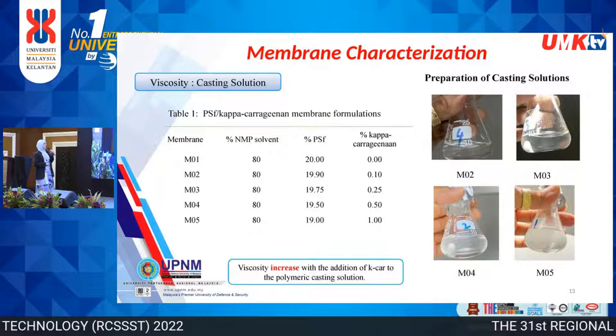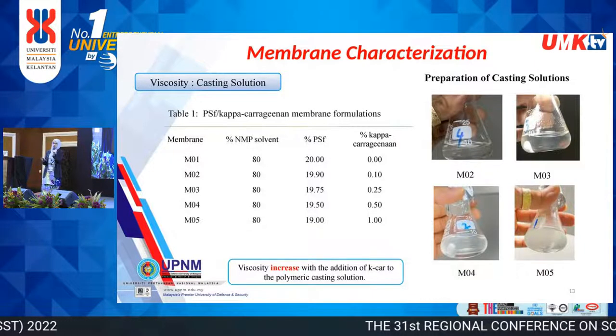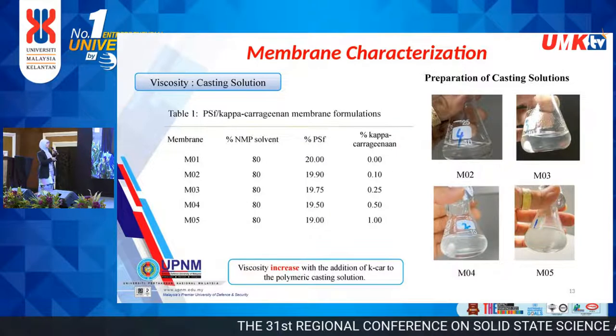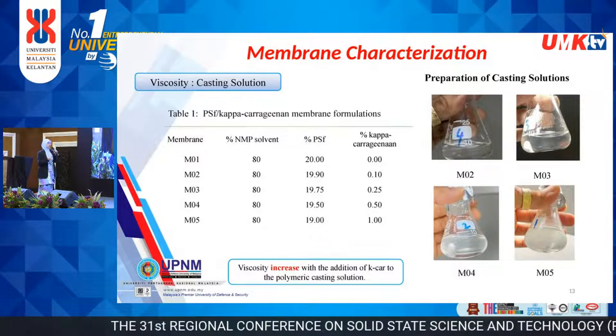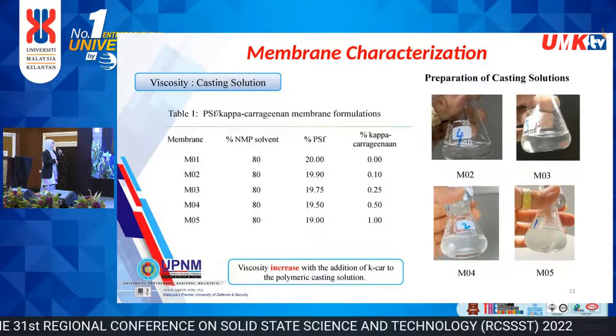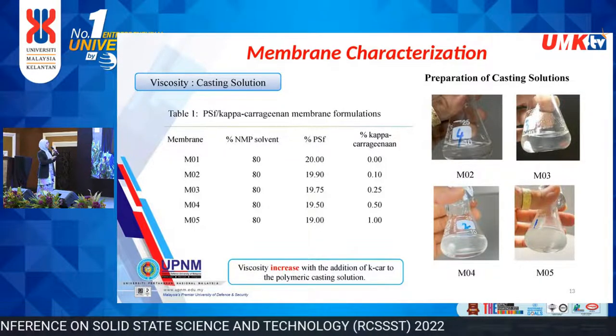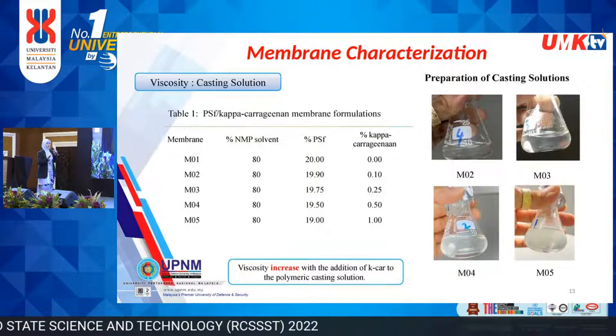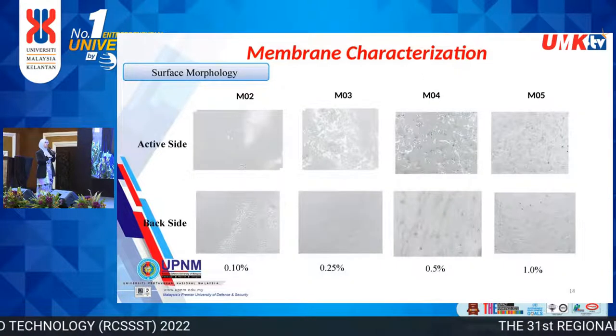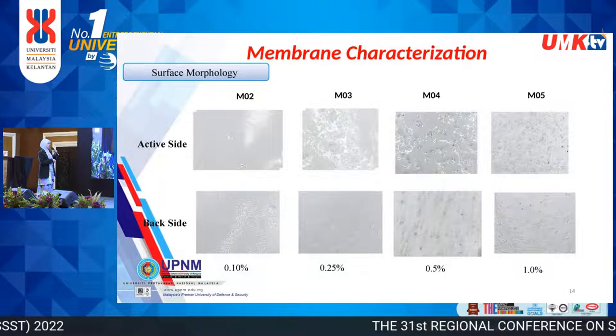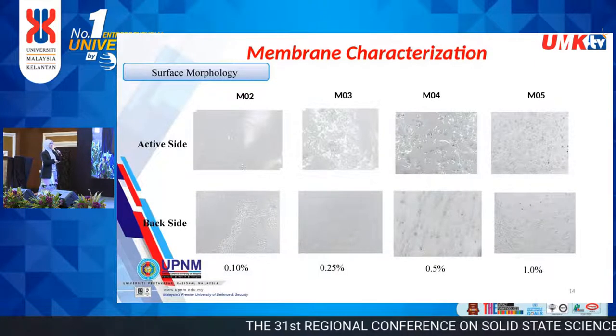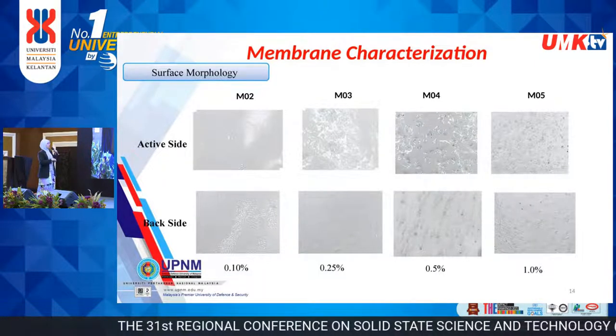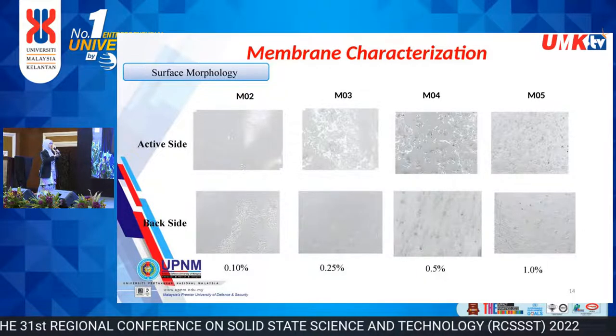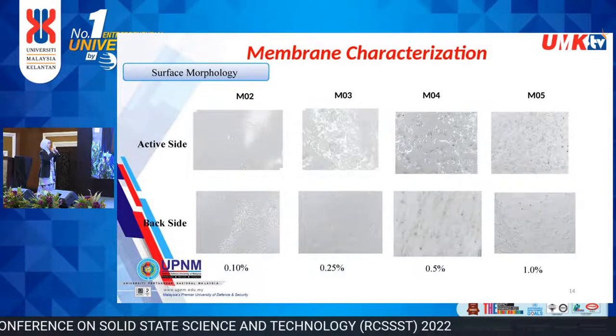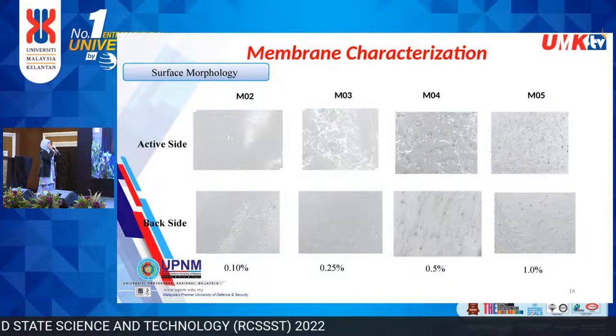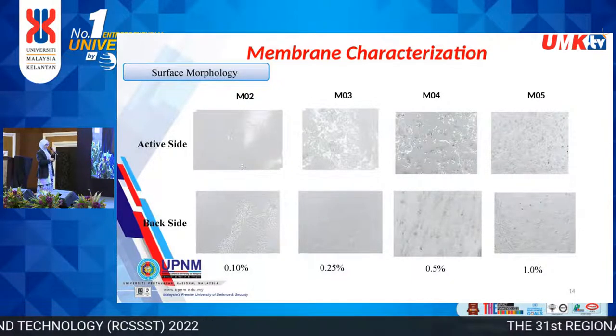Okay, so these are not FESEM images. What we show here are images captured using a high-end camera. These four membranes are the fabricated membranes that we blended with kappa carrageenan, with a percentage of about 0.1 to 1%. What we can see here is that by increasing the percentage of kappa carrageenan, there are more pores on the membranes.